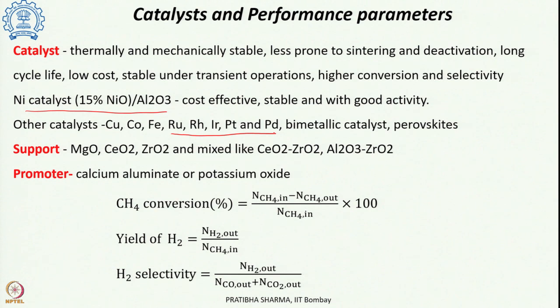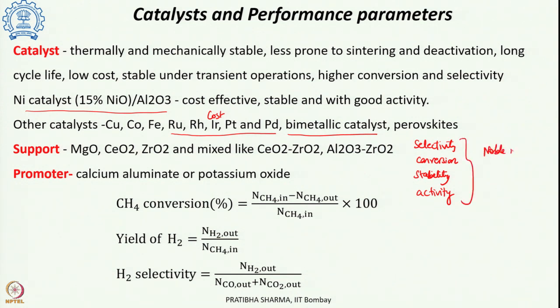The noble metal catalysts have a better conversion, they have a better selectivity, at the same time they are less prone to sintering as well as deactivation. But the cost is the major challenge while using noble metals. As such, the two can be combined to form a bimetallic catalyst wherein a certain amount of noble metals can be used along with the transition metal elements. So, all the three purposes can be met at the same time, getting a better selectivity and conversion of the reactants, having a better stability towards deactivation and coking, and the most important, having a good activity. So, a small amount of noble metal catalyst combined with a non-noble metal catalyst can be used.